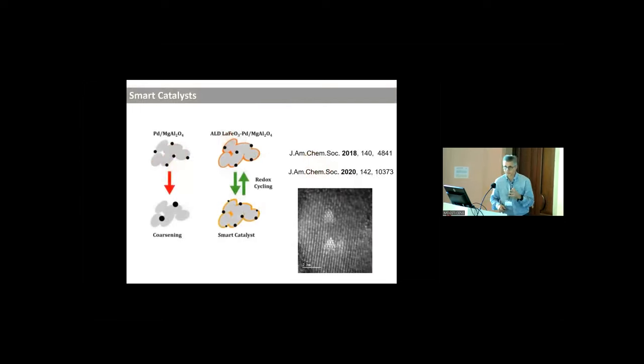I mentioned the synthesis was really a clever synthetic, molecular approach with lots of solvents, organic solvents, diluted conditions. So companies were interested in the performances, but not in the way we make this system. So we try to modify, keeping the concept of protected nanoparticles, and we came out with atomic layer deposition that was of interest also for companies. And by covering conventional supported material with a thin layer of reducible oxide, we were able to make what we call